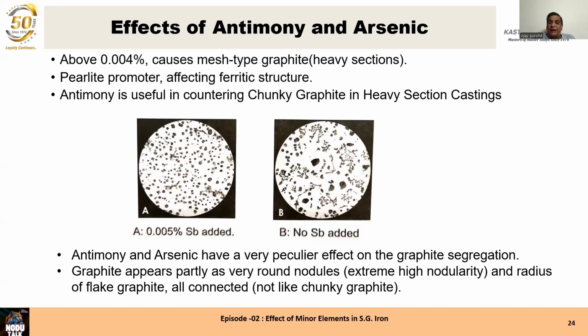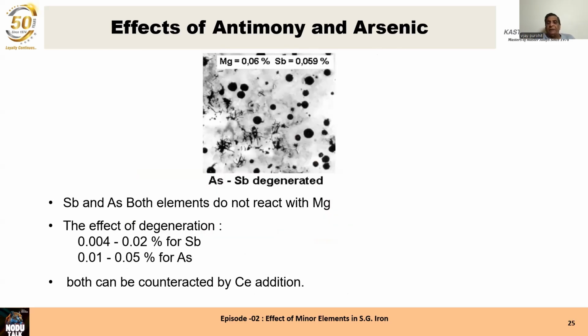In chunky graphite, the graphite particles are all isolated. In this type of segregation with antimony, the graphite particles are all connected. They form graphite flakes all connected, not like chunky graphite. Effects of antimony and arsenic.